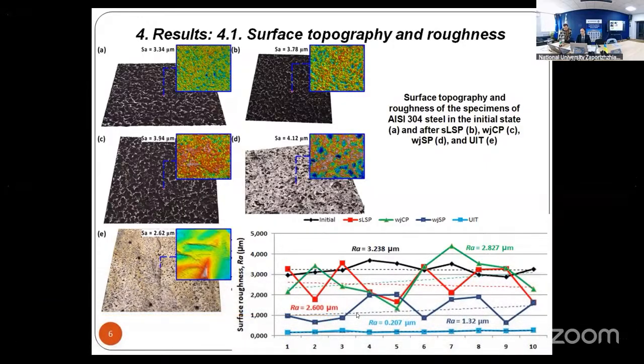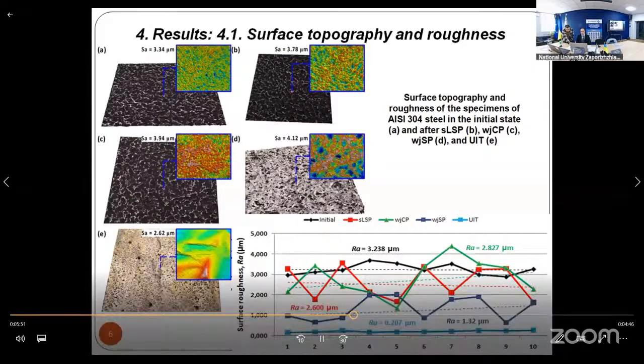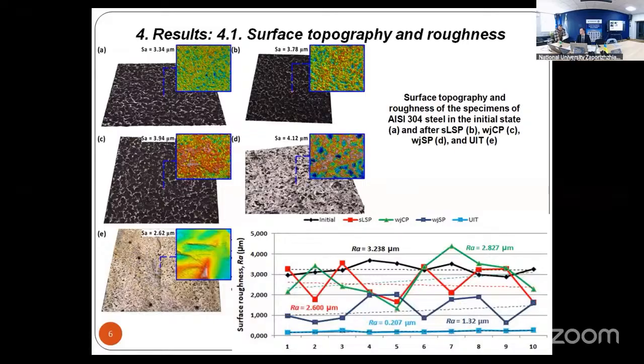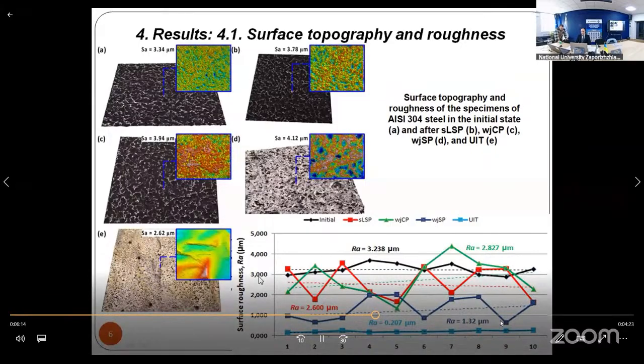The surface was completely modified after the ultrasonic and shot peening, while the laser and cavitation treatments led to minor change in the surface relief due to the rather roughness of the original specimens. This is attributed to the plastic deformation by laser shots and cavitation bubbles, which occurred mainly with micro irregularities of peaks. The surface microrelief of the ultrasonic treated sample is remarkably smoother. Here you can see after ultrasonic, the roughness was the best as compared to the other peening techniques.